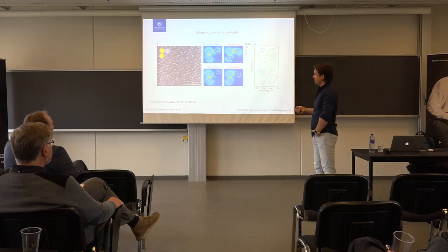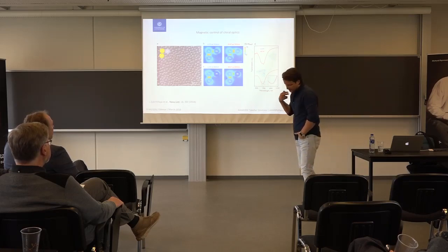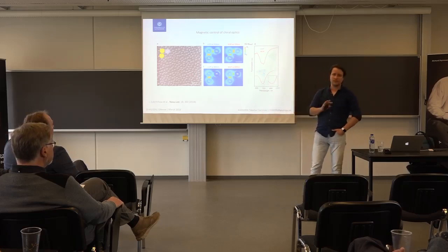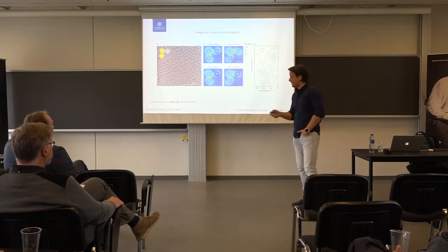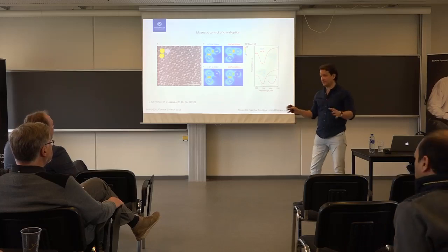This is just a surface that is filled with these antennas. These are trimers. So when the trimer is made of purely gold nanodiscs, it is symmetric, and what we measure is the difference between the transmission of right and left circular polarized light. In chemistry it's called circular dichroism. Here it is a little bit more complicated with the naming because, well, we better stick to differential transmission, okay?